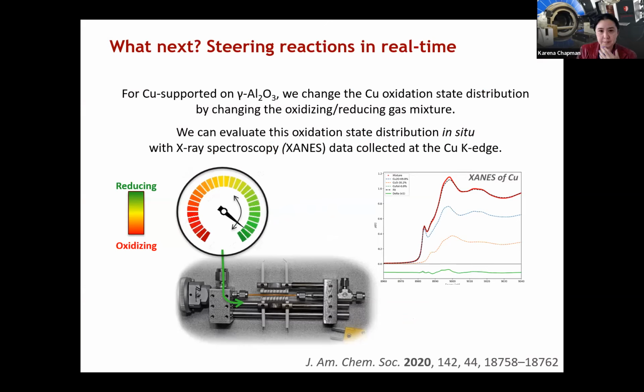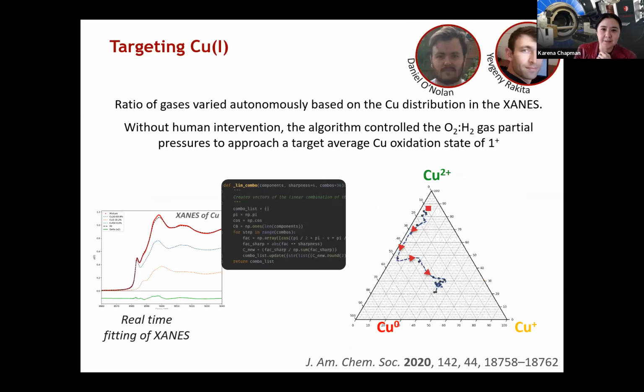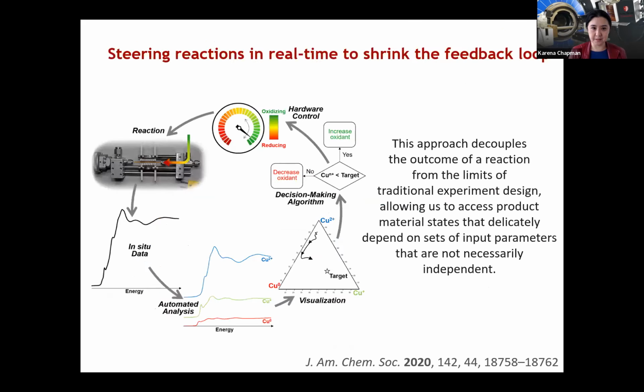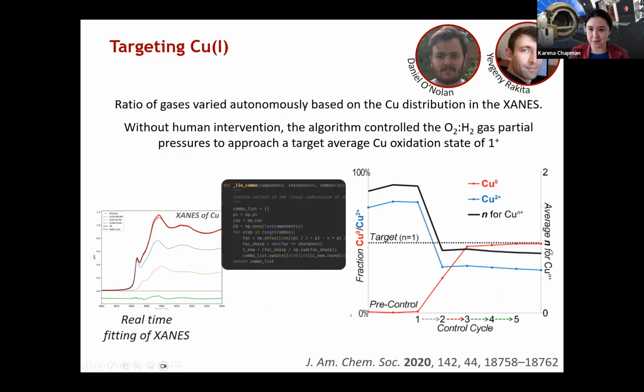So we set up to do these experiments at 9pm. This was the last experiment that we did before we were locked out for the pandemic. This is work done by Daniel and Yevgeny in Simon's group. What they did was write an algorithm that did a linear combination fitting to the XANES data as it was collected, which figured out the average oxidation state, and then either increased the amount of oxidizing gas or increased the amount of reducing gas in order to steer towards the target oxidation state of copper 1+. The good news was it worked — we got to somewhere close to copper 1 after a couple of steps in this case.